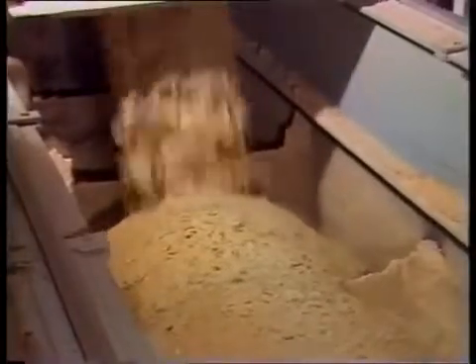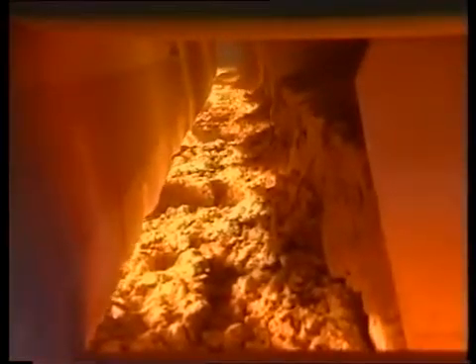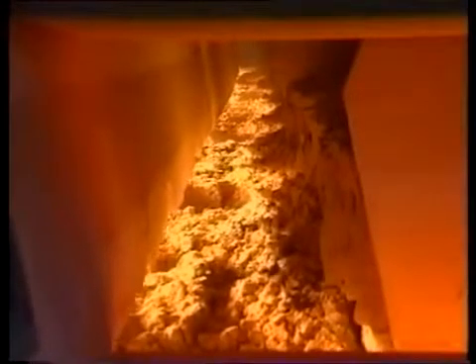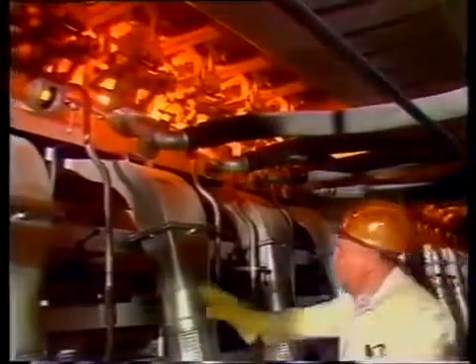All raw materials are rigorously checked to ensure the purity of the batch. It's then fed automatically into the filling end of a furnace with a capacity of 1,800 tons. Natural gas, burned in pre-heated combustion air, then heats the batch up to a temperature of 1,600 degrees centigrade.